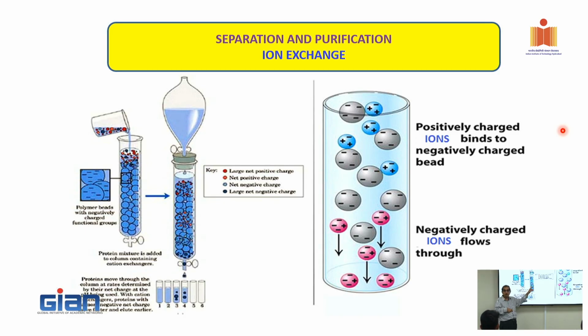So in order to have good loading, your resin is important: how you design the exchange parts of the resin. In order to have better elution, your choice of eluent matters, not only the type, including the concentration. Suppose you take sodium chloride. Sometimes if you use 0.1 molar sodium chloride, only 50% will be eluted. But if you use 2 molar sodium chloride, 100% will be eluted. The reason is that desorption is again based on the law of mass action. As adsorption takes place by law of mass action, desorption also takes place by law of mass action. That is why the concentration and type of the eluent is equally important. So before we choose the entire system, we need to have both the loading curve and the elution curve. Based on that, we will be able to choose which type of ion exchange resin has to be taken.